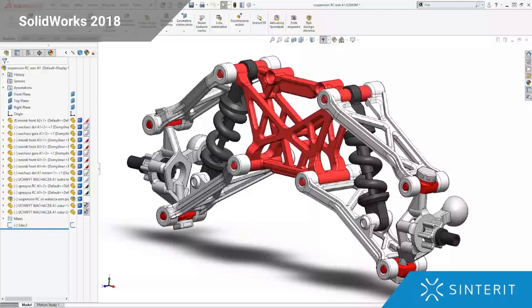Okay, maybe a similar question. My question was about the orientation of the models, especially regarding tolerances for moving parts, axes, etc., layer resolution in Z versus laser resolution in X and Y. Is it something you have to consider before printing? If I understood the question correctly, the best accuracy is in the XY axis. We have customers who contacted us and said the tolerances they received on the XY axis are 30, 40 micrometers. You can't achieve that on FDMs, that's for sure. I don't know about SLAs because I didn't work with them, but Adriana did, so she will probably tell you more in a moment.